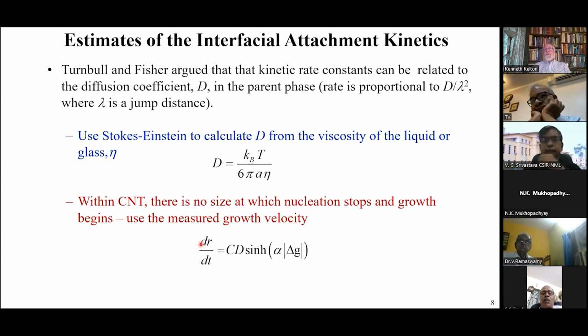As I said, Turnbull and Fisher argued that the kinetic rate should be proportional to the diffusion coefficient in the parent phase. How do we get that? Well, if we're thinking about a liquid and sometimes a glass, you could argue that you could use the Stokes-Einstein relation. The problem with that is that certainly for glasses, the Stokes-Einstein relation is not valid. It breaks down as you go deeper into the supercooled liquid. And even if you get into the liquid, it's possible to go past the point where it begins to break down. So this is probably not the best way.